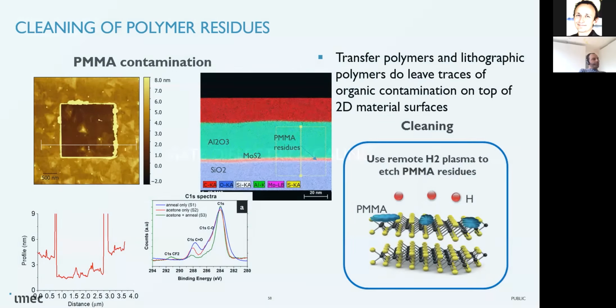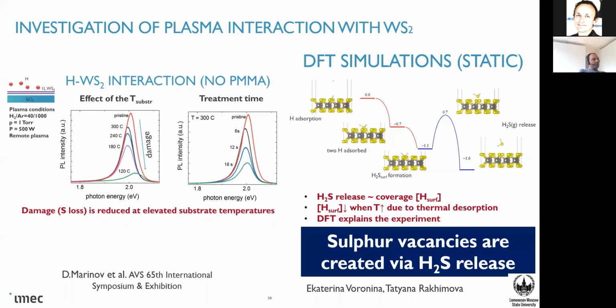Okay, gate dielectric scaling. The transferred layer typically releases some polymer, and there is always a polymer residue that remains on top, and this has an impact on the EOT that you can achieve in these devices. And so it needs to be removed. Therefore, we developed a hydrogen remote plasma clean, which is a very soft clean, but nevertheless, it can still induce quite some defectivity in your material.